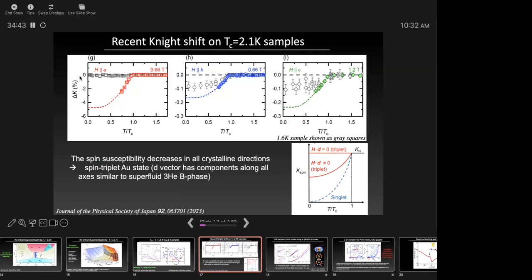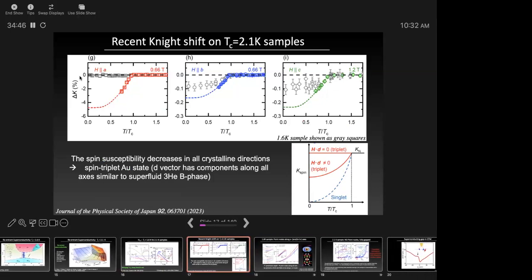Okay, so let me now finally, with all this background, show you the Knight shift, which I was saving for the last. Because that's what one goes to immediately to say, oh, it's a triplet superconductor. You know, why do I care that it's a triplet? That's what makes it interesting. So you'd think it's a triplet superconductor. However, let me just show you this. Initially, when they did Knight shift measurements, they found very little change across TC, and everybody said, yay, we found a triplet superconductor, okay? And that's this gray, all this gray data is actually no change across TC. And all of these gray data points were actually done later on.